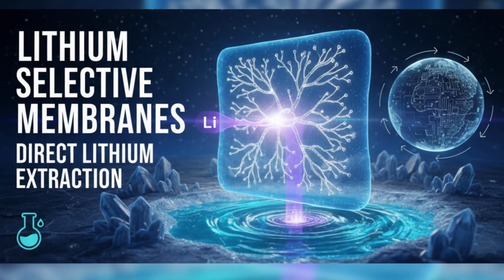We generally group them into three main types: LISICON type, perovskite type, and garnet type. In all of them, the idea is that Li+ can hop between specific sites through these rigid channels, while larger or differently charged ions just can't fit or move easily. Can you give an example, say, from the LISICON family? Sure. LISICON-type materials like LATP or LAGP, that's lithium aluminum titanium phosphate or lithium aluminum germanium phosphate, show amazing performance. The bottleneck size is key. How amazing? Well, one study using LAGP reported a separation coefficient, alpha, of 17,900 for lithium over sodium. 17,000? Yes, and for lithium over magnesium, Mg2+, it was even more staggering, 1,476,000. Over 1,000,000 to 1 selectivity against magnesium.